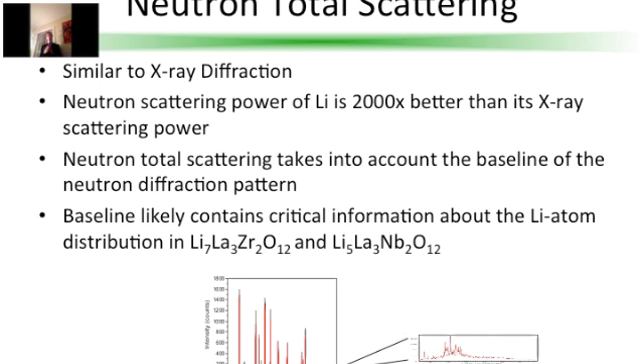Now, ultimately I want to use neutron total scattering to identify the exact distribution of lithium atoms in lithium lanthanum zirconate and lithium lanthanum niobate. Neutron total scattering is a very similar technique to X-ray diffraction, but a major difference is that some materials scatter neutrons better than X-rays, and that happens to be the case with lithium. In fact, lithium scatters neutrons 2,000 times better than it scatters X-rays. This means that we can tell significantly more about the arrangement of lithium atoms from looking at neutron diffraction data.